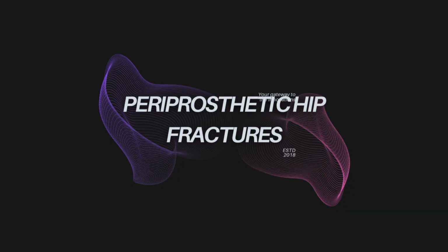You want to lock that bone exactly where it is so the press fit of the stem isn't compromised. If you introduce elasticity into the fixation, you are inherently allowing micromotion at the fracture site. And as you pointed out earlier, micromotion is the enemy of primary bone healing and the enemy of uncemented stem osteointegration. But if you use a perfectly rigid metal cable on a viscoelastic biological structure, the bone will eventually yield to the metal. We see this in stress shielding and cortical notching.